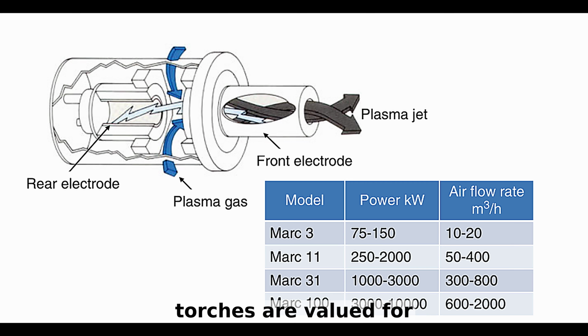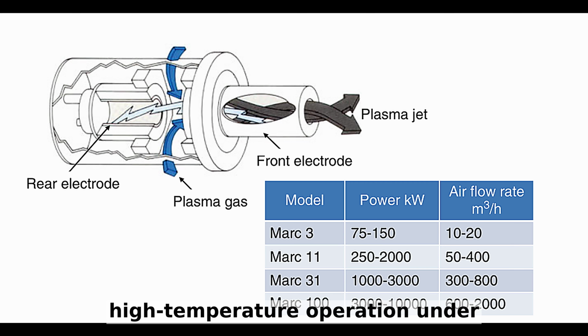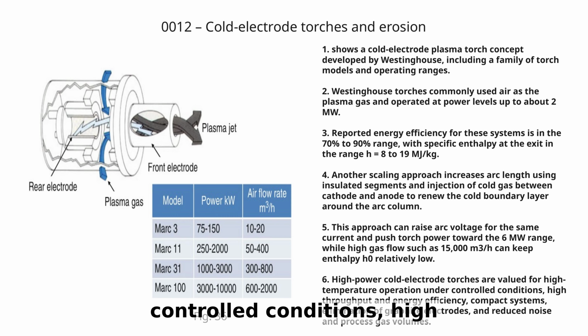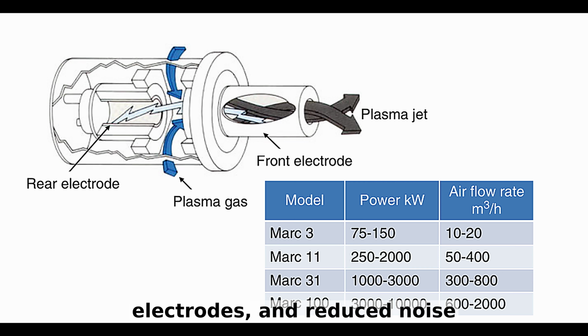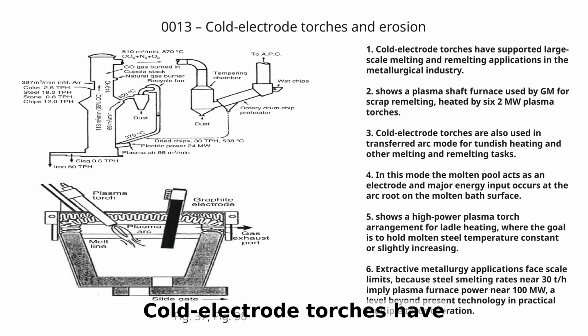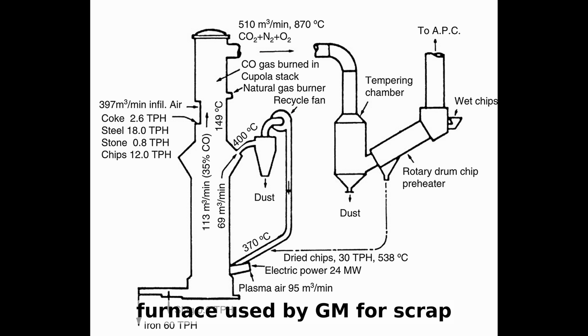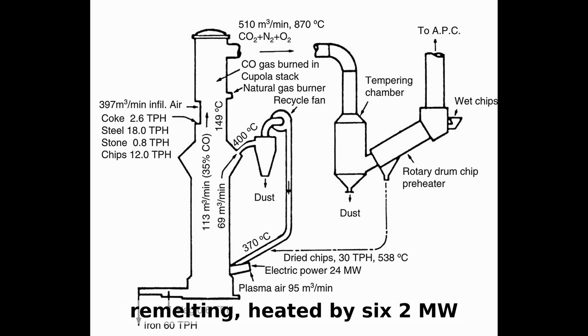High-power cold electrode torches are valued for high-temperature operation under controlled conditions, high throughput and energy efficiency, compact systems, elimination of graphite electrodes, and reduced noise and process gas volumes. Cold electrode torches have supported large-scale melting and remelting applications in the metallurgical industry. Figure 37 shows a plasma shaft furnace used by General Motors for scrap remelting, heated by six 2-megawatt plasma torches.